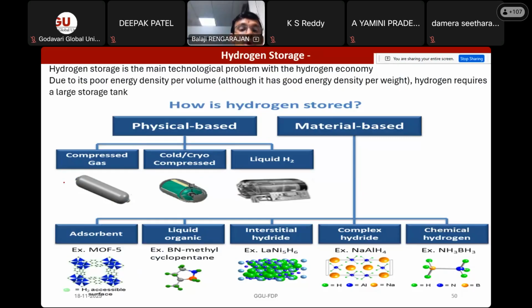So obviously you have to compress the hydrogen to an elevated pressure of 700 bar or 300 bar. If you want to compress the gas to elevated pressure, you cannot use steel. You have to use carbon composite material based cylinders, which can handle high pressure hydrogen, avoid the hydrogen embrittlement phenomenon, and are also lighter weight. But such technology is not available in this country right now. It is being developed. So compressed gaseous storage, especially for transport applications, is one of the key challenges.